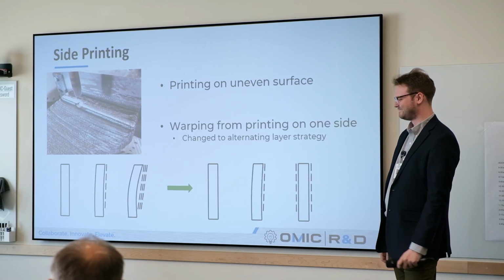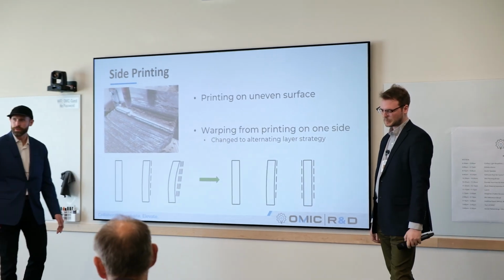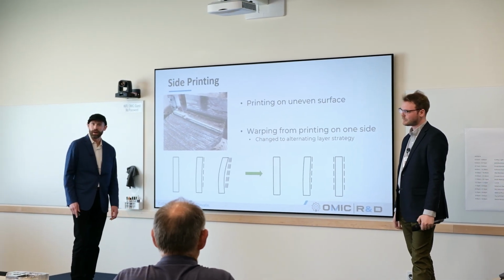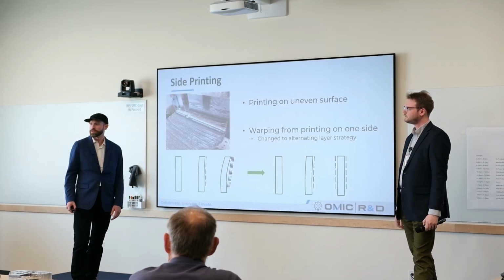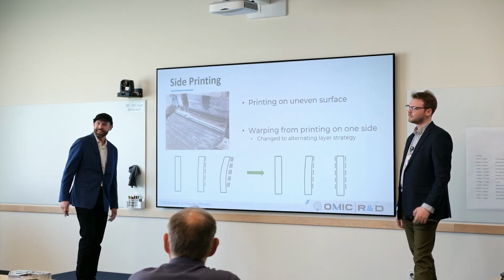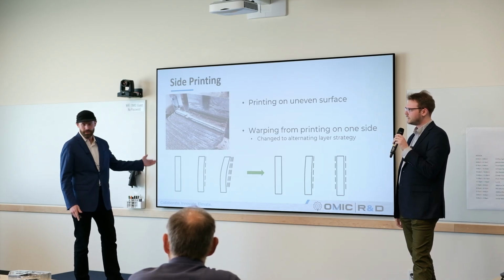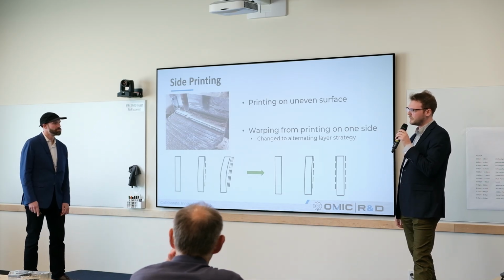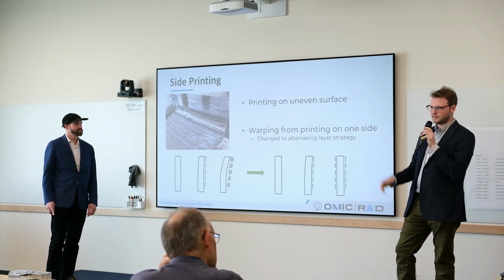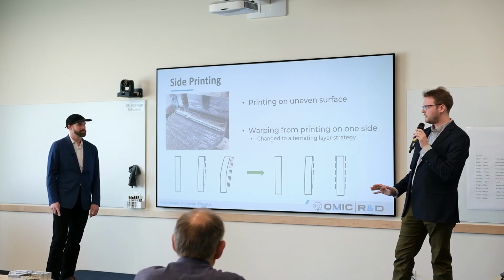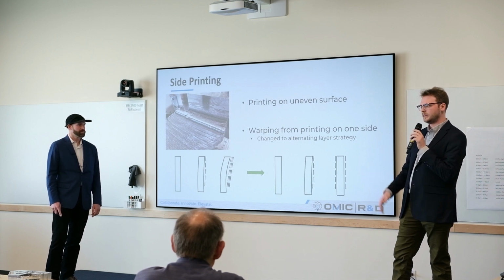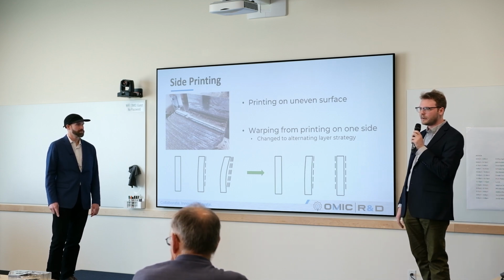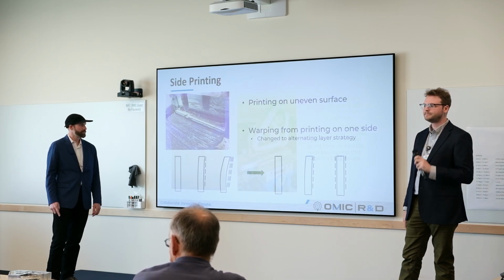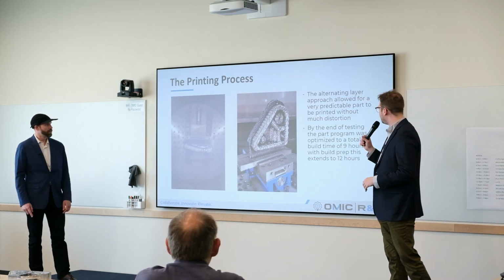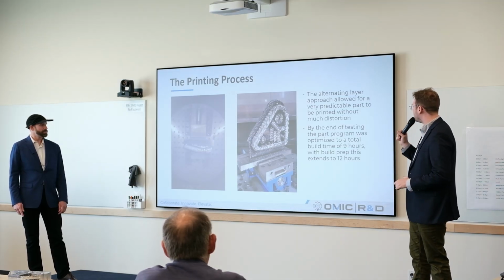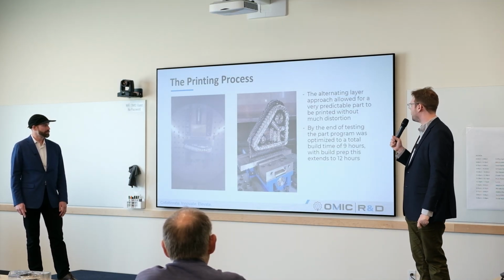And all of those center spine supports were actually very straight when we got to them. The only real change was the build up from side to side and how tall the spines were. The straightness due to this came out almost perfect. Yeah, the spine is the best datum feature that we can provide out of these WAM parts for this particular application. So creating as straight a spine as possible is our biggest benefit. And so this allowed us to have a very predictable part to print, without much distortion.